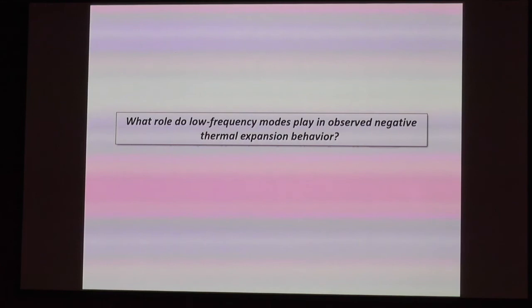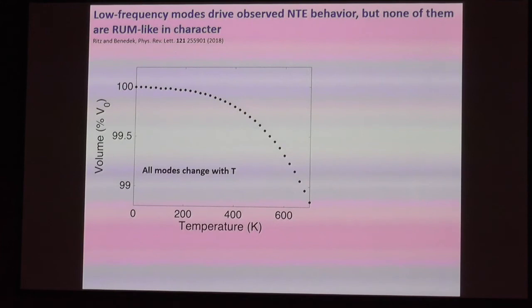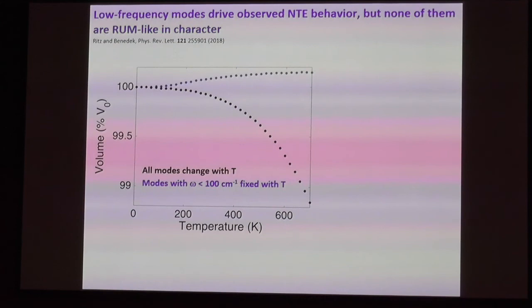Okay, so this is our data again, but showing volume, rather than the two A and C lattice parameters. And okay, it's going down with temperature. And then we performed a little experiment where we asked, well, what would happen if we forced all modes with frequencies below 100 inverse centimeters to be perfectly harmonic? So in other words, we forced their frequencies to stay constant with temperature. And when we do that, then we see that the negative thermal expansion behavior is completely suppressed, and we get